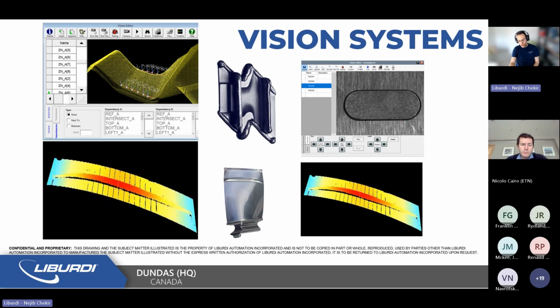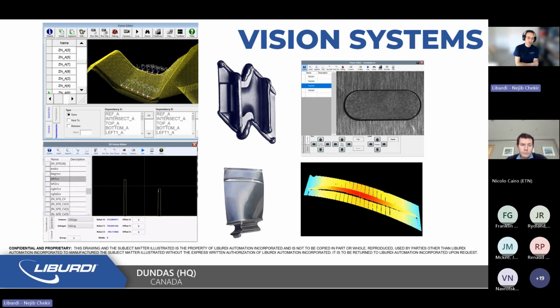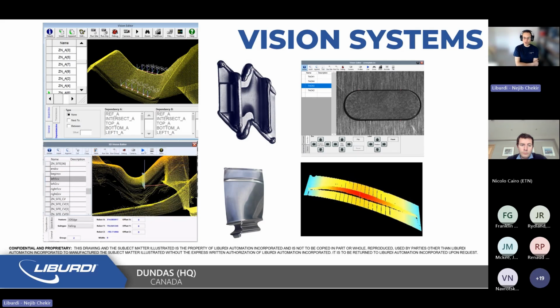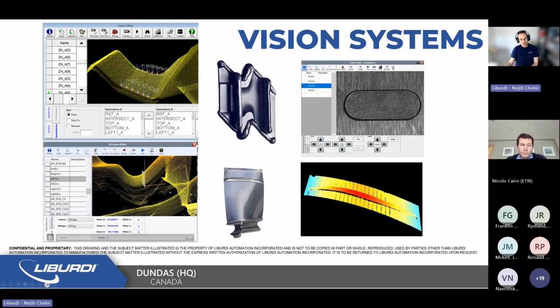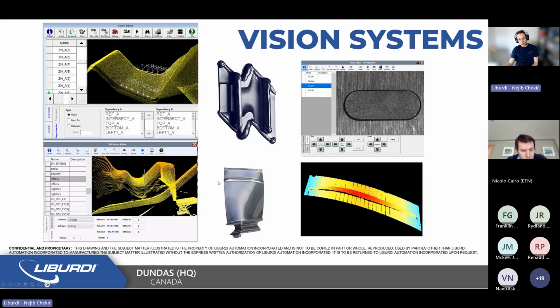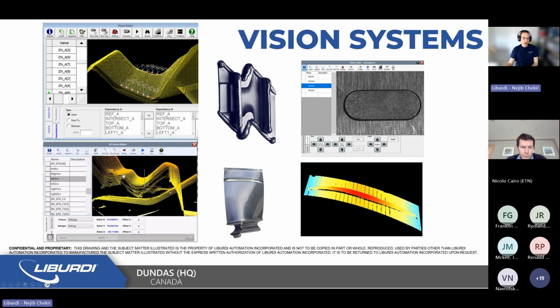Another solution for more complex geometries, those would be geometries in 3 dimensions. So that would be any complex geometry that includes the XYZ components. In this case, what you can do is use a laser scanner that can generate a 3D point cloud. On the bottom left here, you can see an example of a scan that was generated for low pressure turbine blades, the Z-notch area.